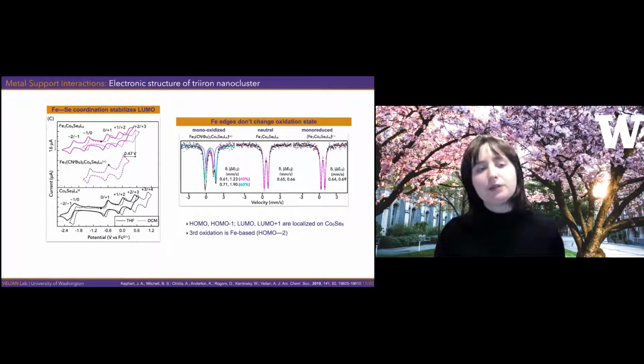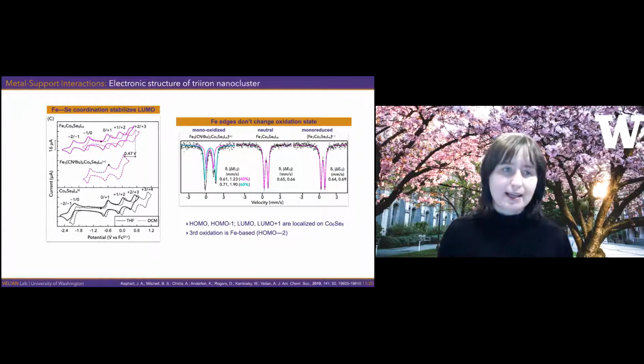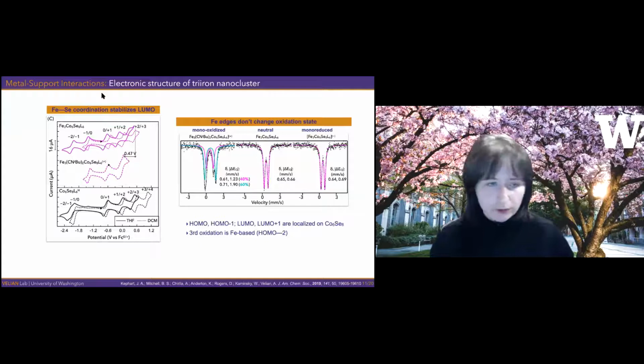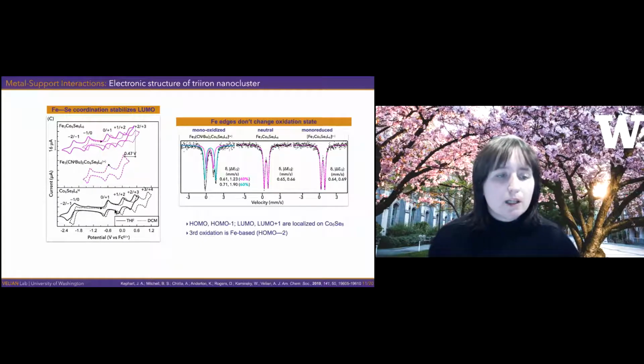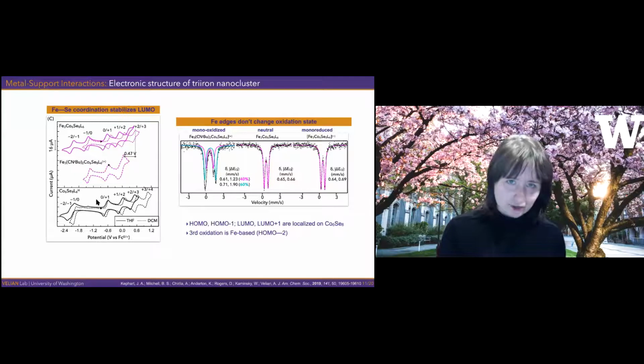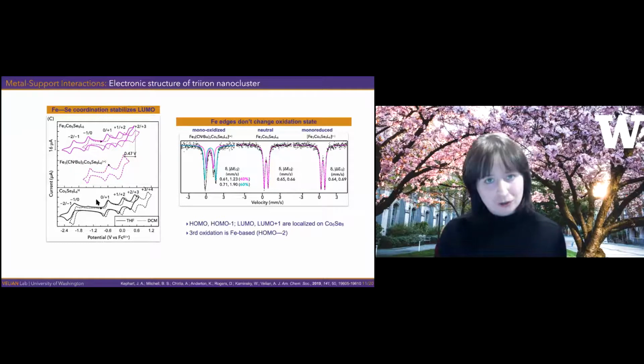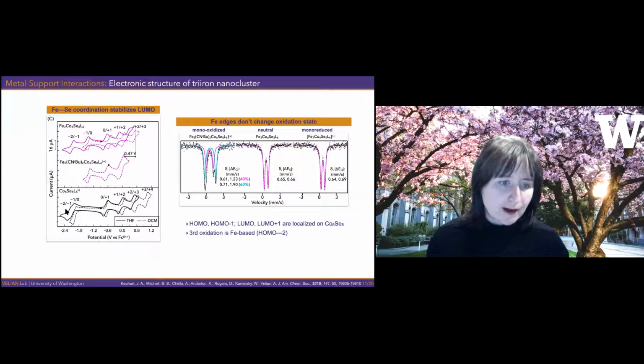But to really dig into the electronic structure, what we used, and the reason why we started with iron edges, is electrochemistry and Mössbauer spectroscopy. Okay, so on the left is electrochemistry. I'll walk you through it. The reason why we really love this cobalt selenide cluster is because among other things, it's very stable to taking and putting electrons in. It changes very little geometrically, so it's quite robust, and you can really cycle through many electrons, like 1, 2, 3, 4, 5, 6, and they're all chemically reversible.